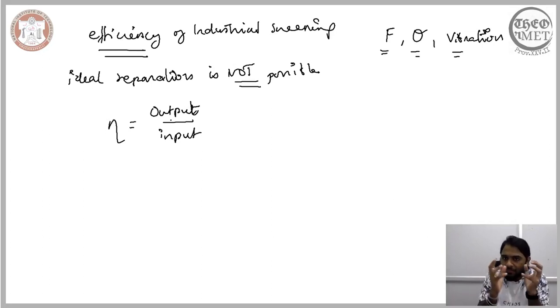The purpose of screening in a conventional manner is to provide feed for the subsequent process in the comminution, so the screening process is placed between the tertiary crusher and the grinding. What the screening essentially does is ensure that the right particles are fed into the grinding. So the particles that are smaller than the aperture are the desired output for conventional screening.